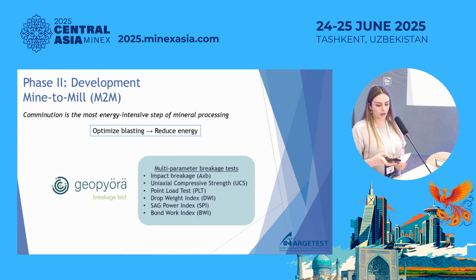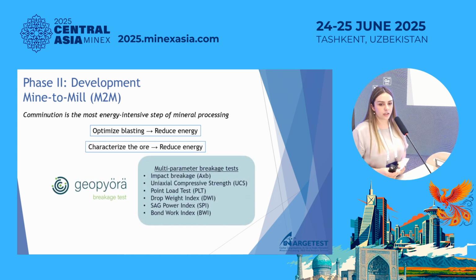Here, multi-parameter breakage tests are actually really useful. So we are partnering with geopyörä for breakage tests that actually use a small amount of sample to perform all of the breakage tests. For example, the first 3 are for crushing and the last 3 are for SAG mills and ball mills, and they are really useful. So as a result, you characterize the ore in the very beginning, and then you optimize your blasting, and as a result, you optimize your grinding.